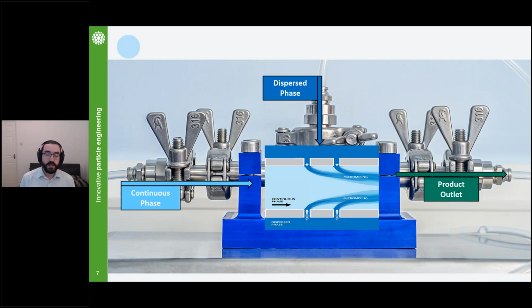These membranes that we're placing inside are essentially a very much scaled up version of similar single pore systems. So if you're familiar with microfluidics and single junction T mixers, imagine 1.7 million of those within a tube that's 6 inches long. And that's what we've created with the AXF1 here. And that gives us this excellent scalability and control that we think is quite unparalleled in other technologies that are available for producing these particles.